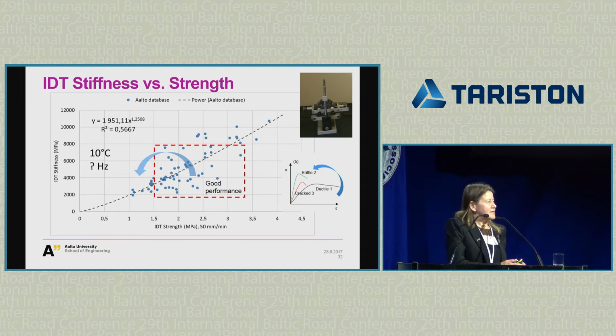And we use 10 degrees Celsius to capture the low temperature performance. What is interesting is that there is no correlation, as there shouldn't be, because with different stiffnesses, depending on what kind of binder you have, you still might have the same strength for the mix, or the other way around, that you have the same stiffness, but a huge variation in the strength. So what is driving what?